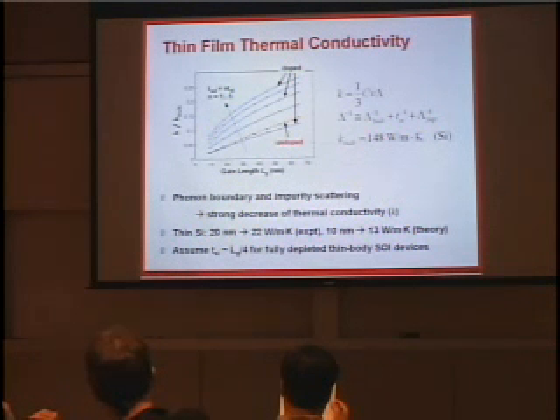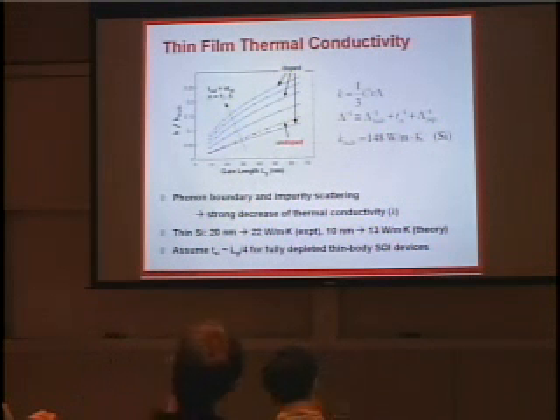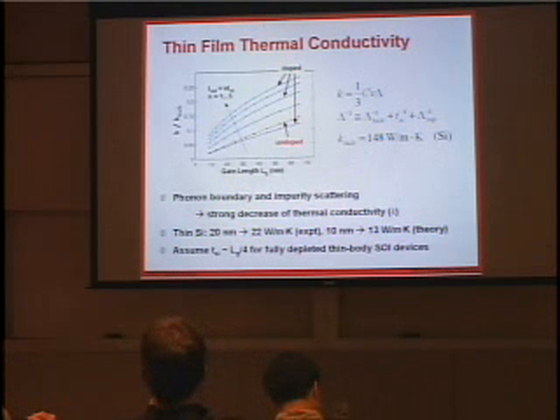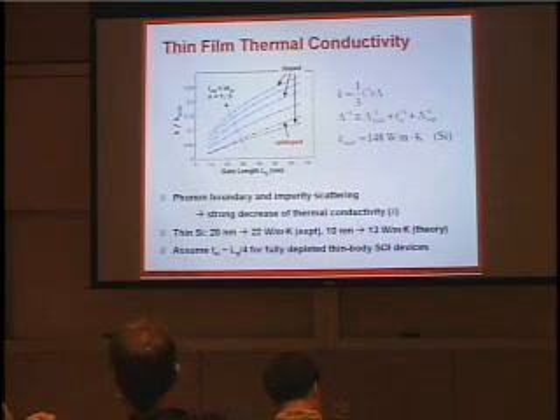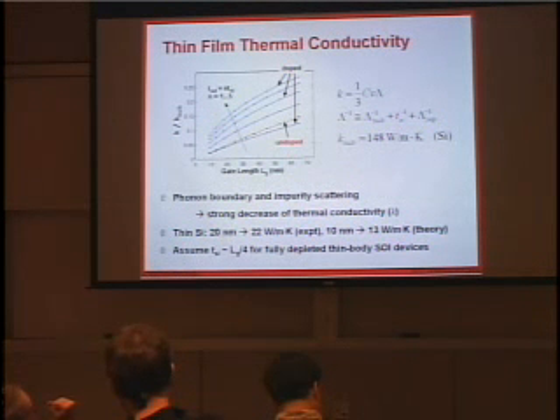In this plot, I'm plotting the thermal conductivity as a function of technology node, and I'm assuming that the thickness of the silicon layer goes as 1/4 the gate length for depleted devices. I'm also showing you what it might mean to make that layer thicker by a factor of 1 to 5. So obviously you get some increase in thermal conductivity that way.